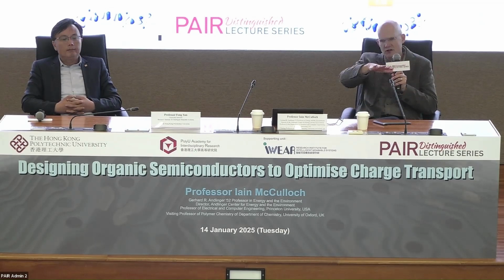And the way that we addressed that to some extent with polymers was the introduction of liquid crystallinity. So when you anneal a polymer, if you have a liquid crystalline phase in the polymer and you anneal above the melt, then in the liquid crystal phase, you can get quite nice overlap between the grains. They tend to orient quite well with respect to each other. It's not such an abrupt interface. They tend to want to flow and have common orientation directions. So the effect of the grain boundaries, if you anneal a liquid crystal polymer within its mesophase, really reduces the effect of the grain boundary.